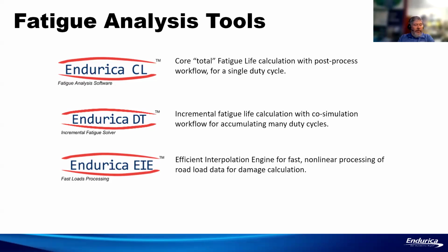In many cases, the histories that you want to analyze are lengthier than you can really analyze directly with a finite element simulation. And so Endurica EIE provides a method whereby you can rapidly convert XYZ global force or load displacement inputs into stress strain history on each element in a model without having to do the full blown FEA. It's very fast. It's like 10,000 times faster than trying to directly do it. So it opens up a lot of analysis possibilities that are important.